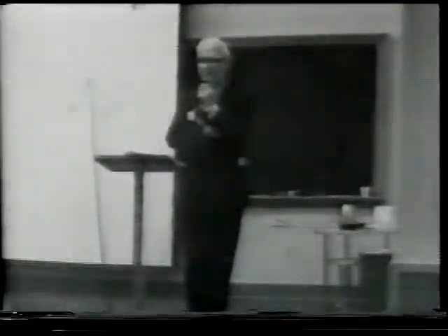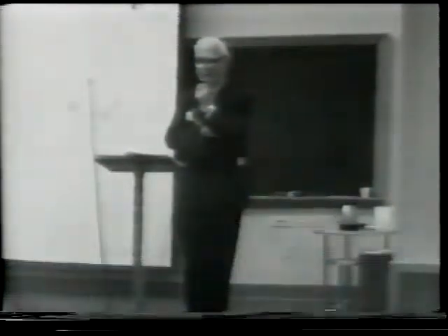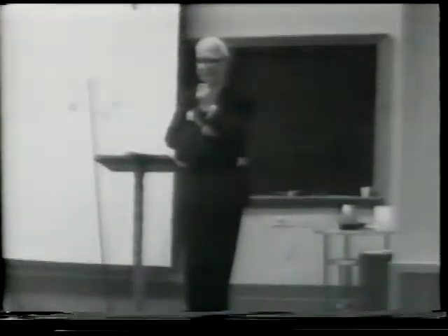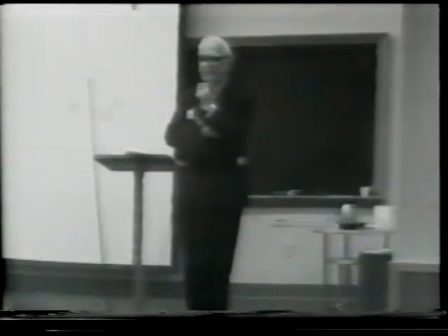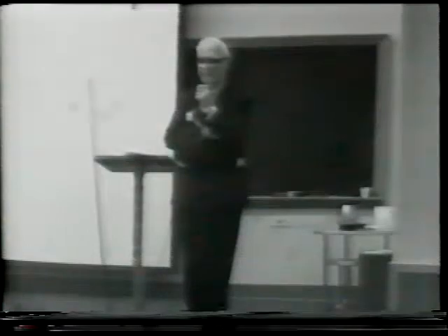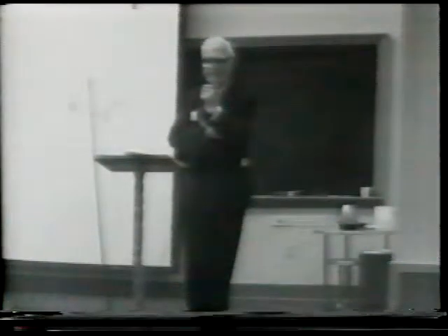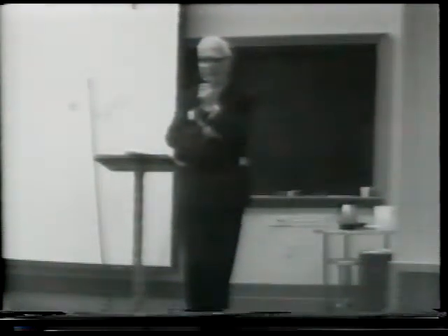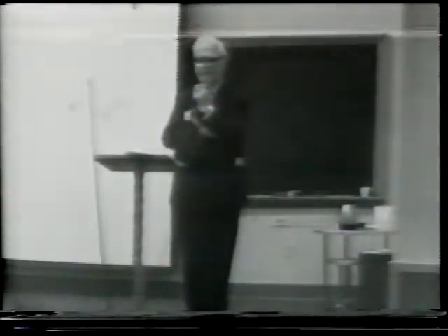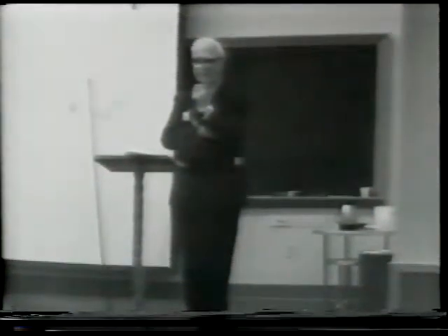Right in this connection, though, I can't refrain from mentioning something that has excited me very much, and that's the very lovely work that Terry Baker, from the Harwell Laboratories, has been showing around the country during this last year. I don't know whether any of you had a chance to see it, but he was working on the oxidation of graphite, and he showed pictures. He had an electron microscope rigged up with about a 25 angstrom resolution, tied in with a television and a movie camera in such a way that he could see the surface quite clearly down to a refinement in the order of 25 angstroms.